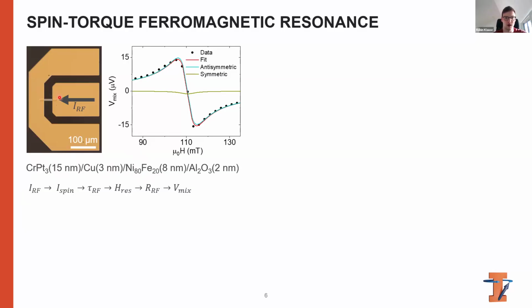So we patterned this into wires and through electrical contacts. The measurement works by passing an RF current through the wire. This generates an RF spin current due to the spin Hall effect, and this gets injected into the ferromagnetic layer where we generate an RF torque.